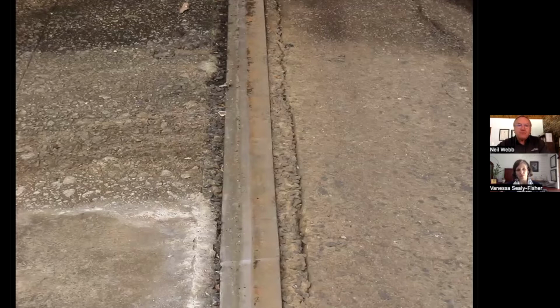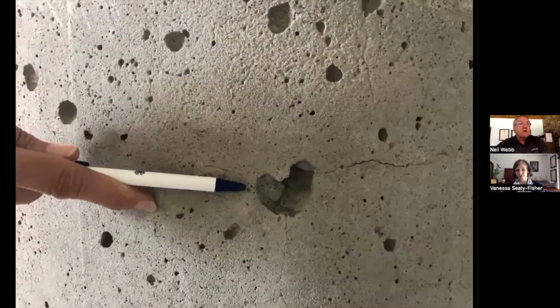So to stop that concrete corrosion, as it were, perhaps apply a coating? Well, yes, and it's not perhaps used very often in dams, but there are many structures where we can coat concrete. And one of the challenges in coating concrete is the actual nature of the concrete itself. And if you look at this photograph, again, you can see that there are voids in the concrete. These are almost impossible to prevent.